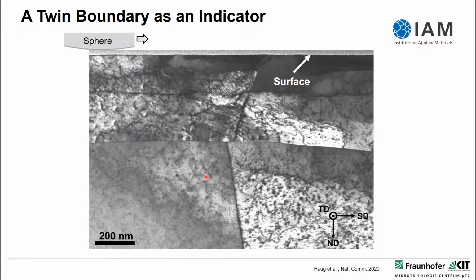What you see again is a TEM foil where we're looking in cross-section at the STEM contrast, taking scanning transmission electron microscopy images inside our scanning electron / focused ion beam microscope. The sphere here again made just one trace moving from left to right. The normal load here was not 2 newtons, it was a little bit more. Experimental details you can read up on in our paper published this year in Nature Communications.